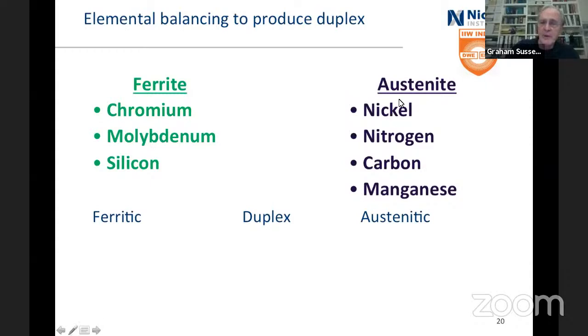Austenitic, well, the nickel, obviously, the nitrogen, obviously, carbon, but the trouble is if you start adding carbon, you wind up with the problem that you had with 200 series, that you get carbides, and so it's very hard to weld. And manganese. Now, one of the things about manganese is you put lots of manganese in and suddenly it becomes easier to dissolve nitrogen. So therefore, putting manganese in gives you 2 for 1. You get a small effect of going towards the nickel process and a larger effect about putting nitrogen in.